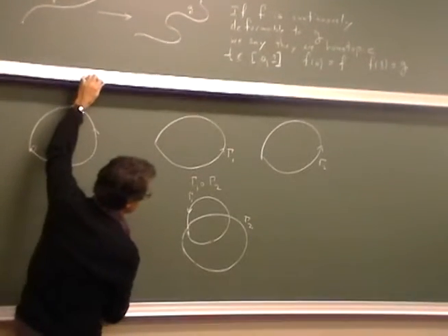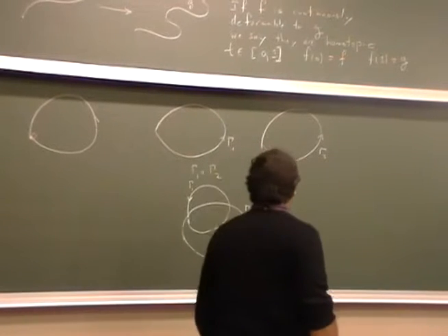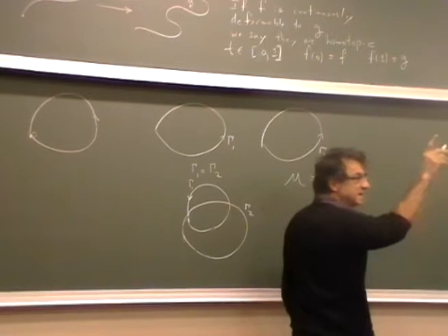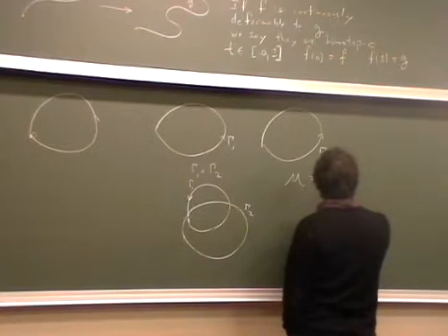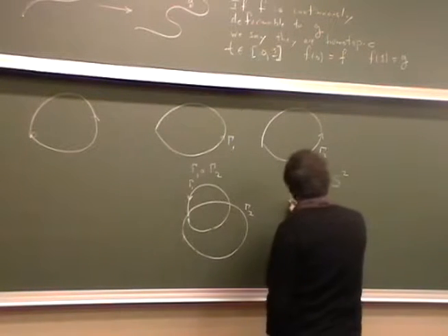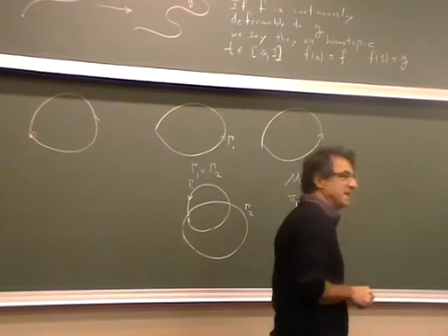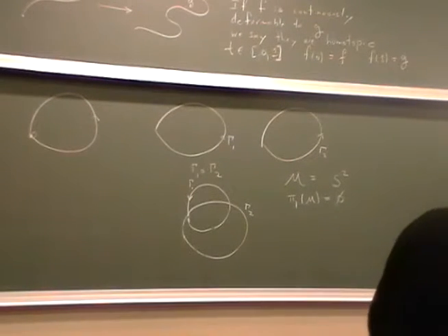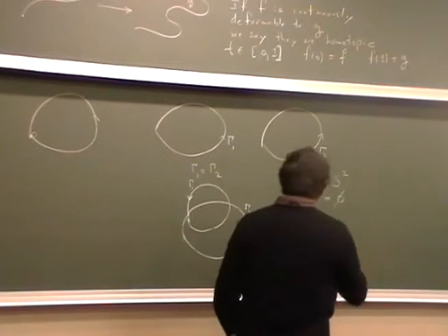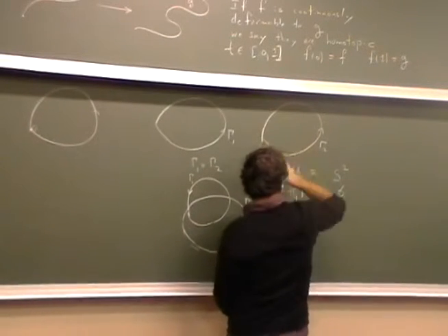So let's review the example we had, and let's give more examples. In the case of ferromagnetism, polar order in three dimensions, M was just S2, and this is simply connected. That's the fact that you cannot lasso the surface of a basketball. All loops are contractible down to a point, no obstructions, none of these line defects we get for pi 1.